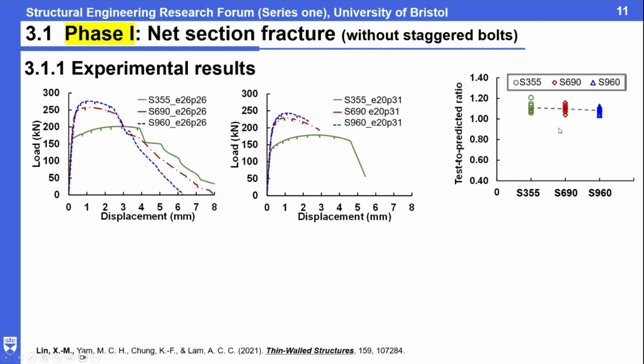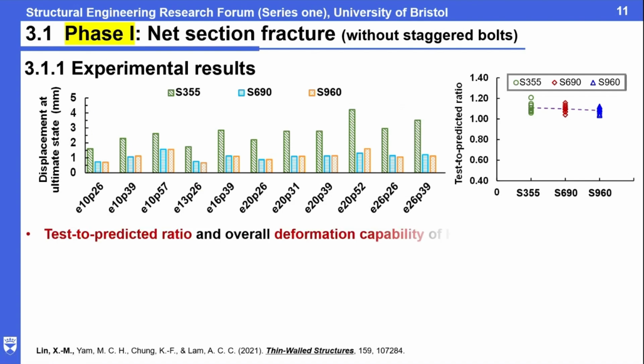And here, this is the test-to-predicted ratio. What does this mean? Let me explain this one first. This is the displacement at the ultimate state. I extracted the displacement for each specimen to do the comparison. The green one is mild steel and the other is high strength steel. You can find that the mild steel displacement is larger, right? So this indicates that the ductility of the bolted connection made of mild steel is relatively larger than that of the high strength steel. This makes sense, compared with the material property.